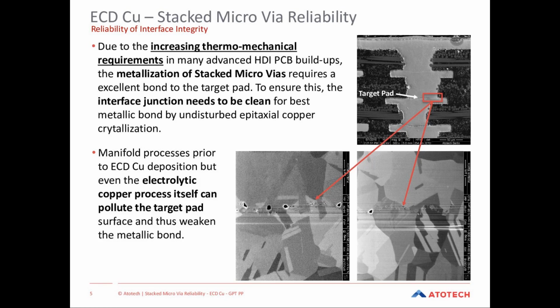So it can be encapsulated hydrogen from electroless copper deposition, but it is also known that electroplated copper creates such micro or nano voiding because of tensile stress inside the copper deposit. So you know that the more irregularities you have in the atomic lattice of copper, the more vacancies you have, the more sliding planes or twins you have, the more the copper will create very small voidings later at grain boundaries. And this can be also one reason to see nano voiding at the end. There are many more reasons, but these are two general reasons why you can run into this nano voiding problem. Okay, thank you. So let's continue with the next question.